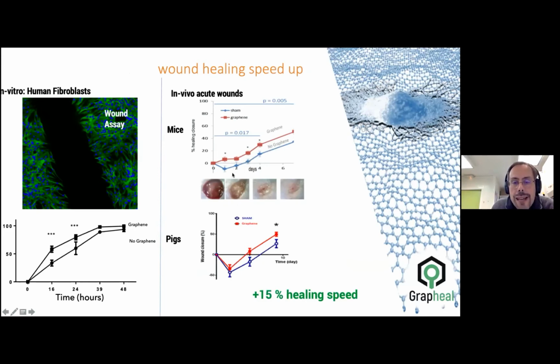If you look at the side, instead of having extension of the wound by inflammatory response and then coming down, you clearly see that there is a closing of the wound in the first few days. And this time here gained 3 days, typically on the mice wound healing. In the case of pigs, it's a bit less prominent, but you have still typically 15% healing speed. In the case of this human fibroblast on substrate, you have also a similar effect.